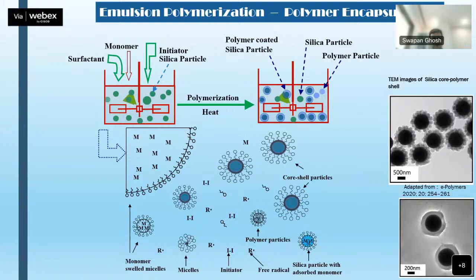Otherwise, to use different types of monomers, some sort of modification we can play with, and most critical is we can play with the surfactant, because the surfactant will be required by two species now. One is the micelles, the polymer particles which are forming, they need surfactant to be stabilized. At the same time, the silicon oxide particles which are also coated by polymer, those also need surfactant. And this balance, if you can play with it, there is always a balance, and in that balance we can reach up to a level, I mean to say nearly 85–90% of the silicon oxide particle can be coated by polymer.